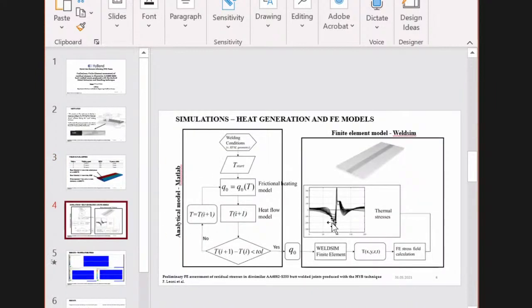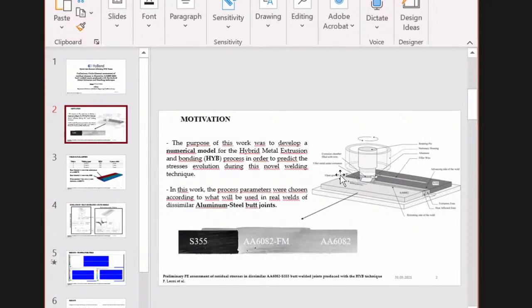The main challenge in simulating this novel welding technique is that this is a friction-driven welding technique, and thus the heat that is generated during welding is caused by friction between the tool and the material that is joined, which is similar to what happens in friction stir welding. But in this case, you have to take into account also for the material which is added to the joint. Indeed, as I show you in this figure, there is an open groove between the materials that are joined, and this groove is filled with a material that is extruded inside the gap.